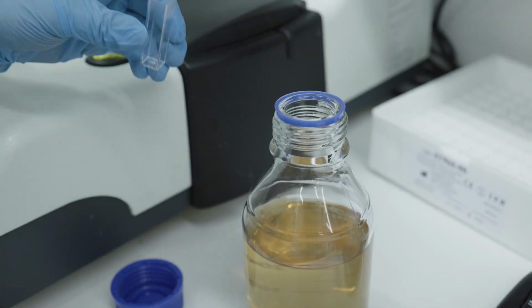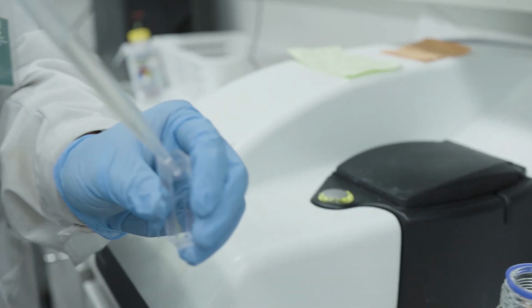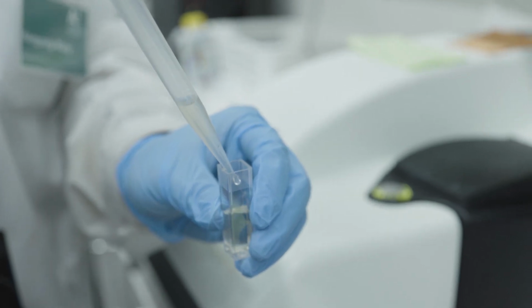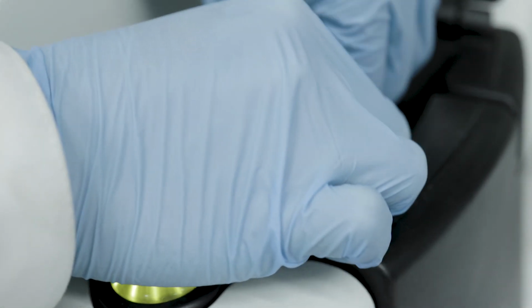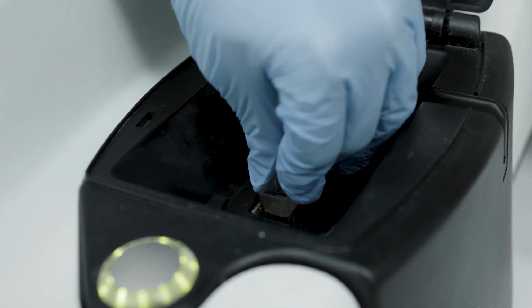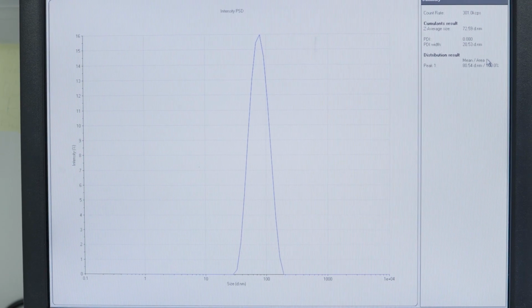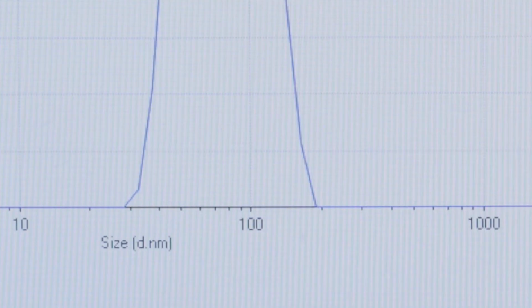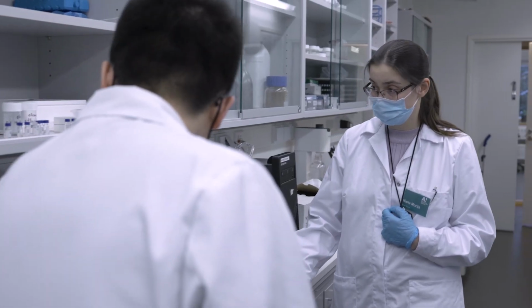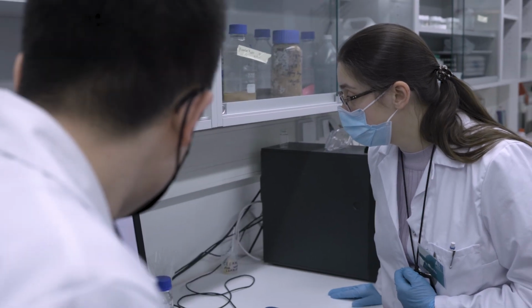The first characterization which we do is a measurement of size of these particles. For this purpose, we use dynamic light scattering (DLS) technique. This method provides us with the average size of particles, size distribution, but it doesn't give us information about morphology of the particles. Also, we can suspect that we have aggregates in our sample if we see some unexpected results, unexpected measurements.